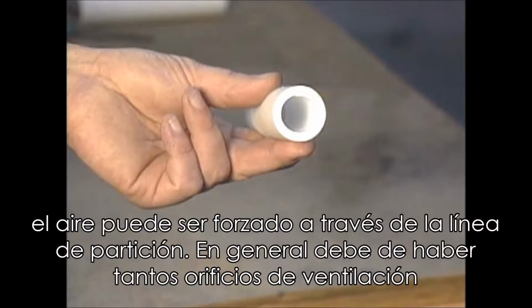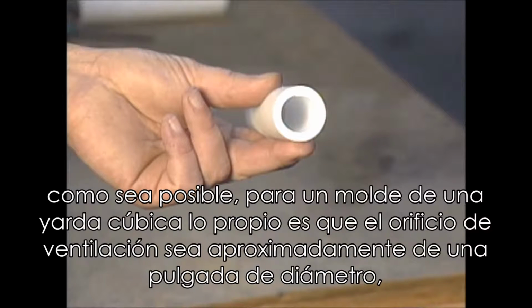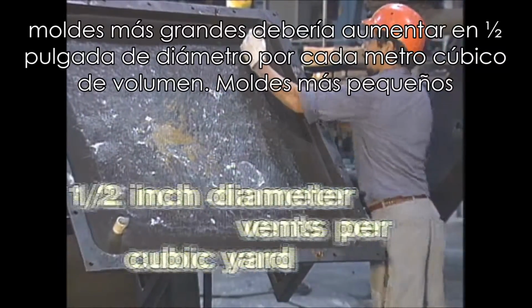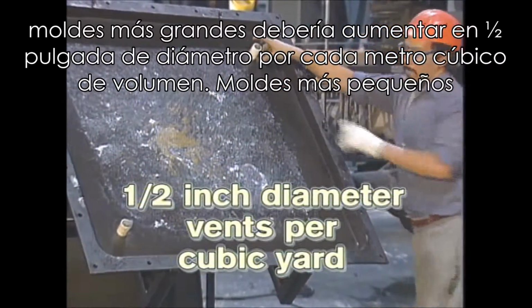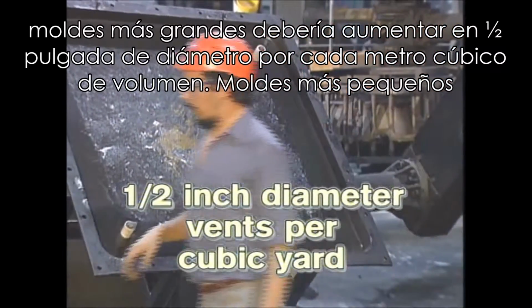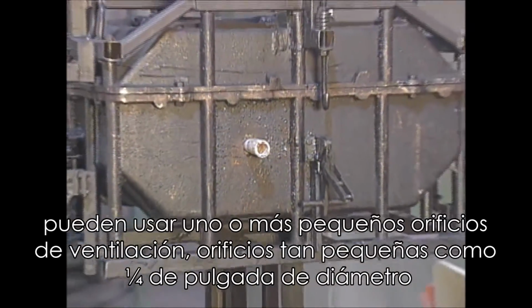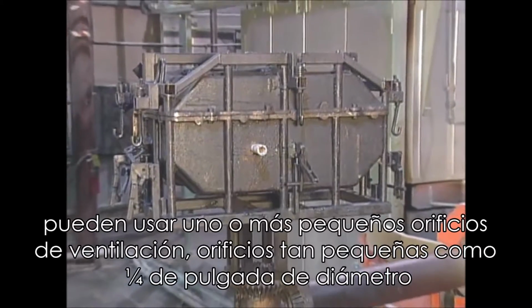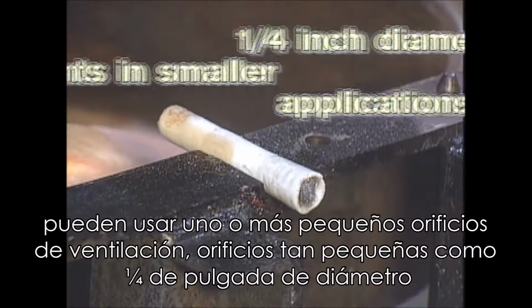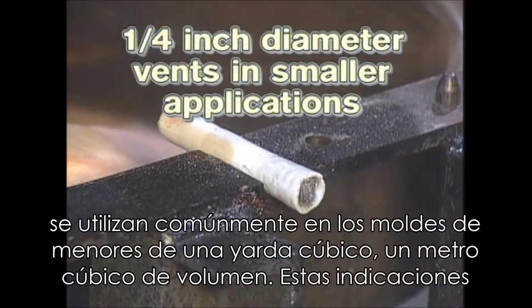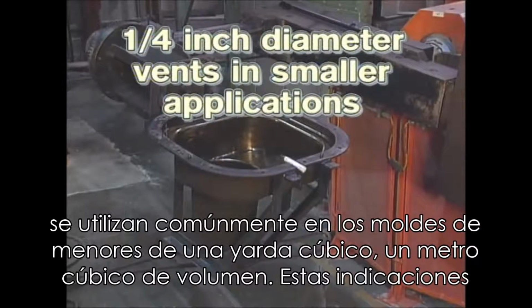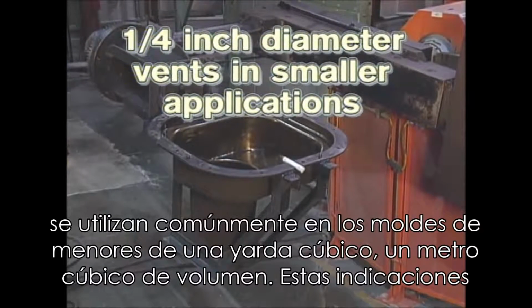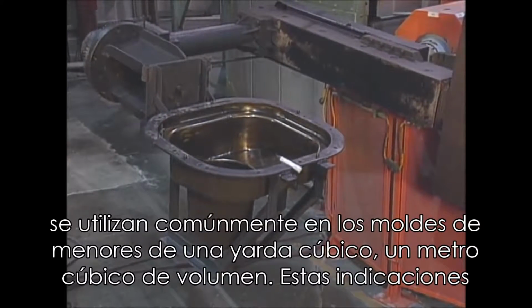Generally, there should be as much venting as possible. A 1 cubic yard mold will typically have approximately a 1-inch diameter vent. Larger molds should increase by a 1/2 inch in diameter for every cubic yard of volume. Smaller molds can use one or more smaller vents. Vents as small as 1/4 inch in diameter are commonly used in molds less than 1 cubic yard, 1 cubic meter, in volume. These guidelines are based upon practical experience.